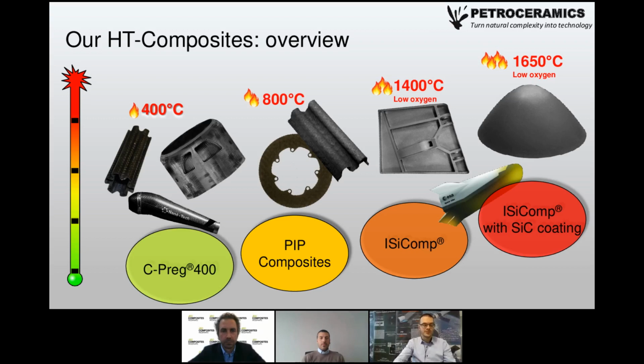And so our composites for high temperature applications are all carbon fiber-based composites. And as you can see, we have a wide range of temperatures. We can start with Cpreg 400, that will be described in depth later together with Nano-Tech, which is thought to work up to 400 Celsius degrees. But there are applications which require even higher temperatures and resistance to prolonged exposures. And for this application, we propose the Cpreg PIP composites, which can withstand 800 Celsius degrees.